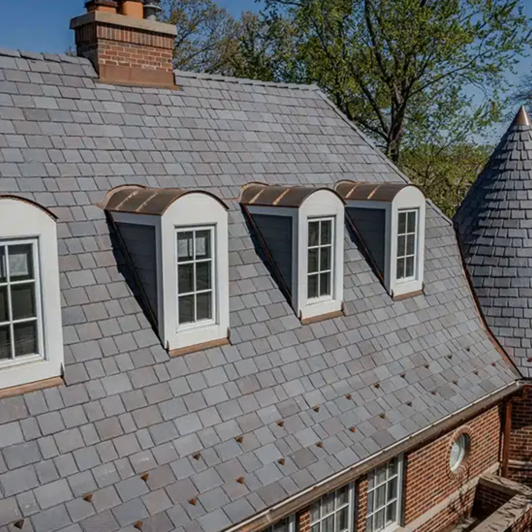But, like everything else, it had its limitations. Clay is slightly porous. If water gets into a microscopic pore in the clay and then freezes, the water expands by 9%. That expansion pressure can reach 30,000 pounds per square inch, enough to shatter the tile from the inside out. That's why you rarely see clay tiles in places with snowy winters. The other reason terracotta isn't seen everywhere is that it is also heavy, just like slate.